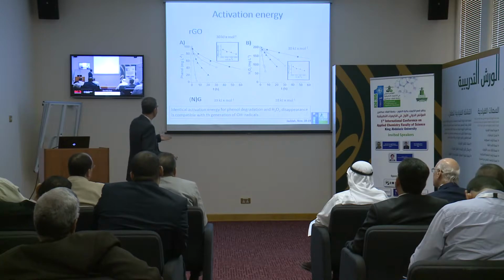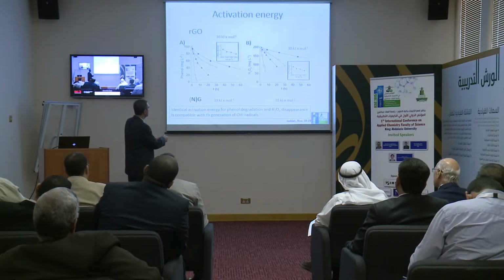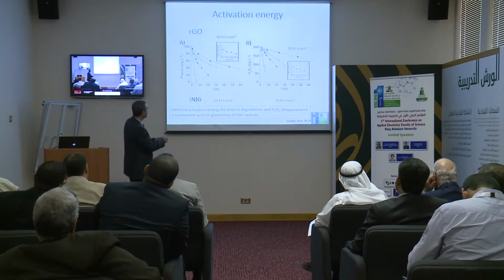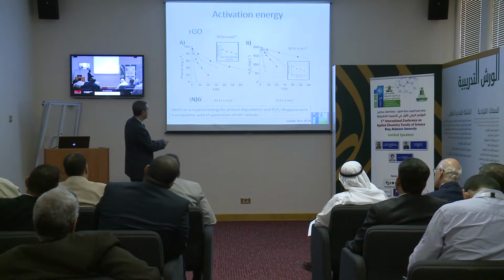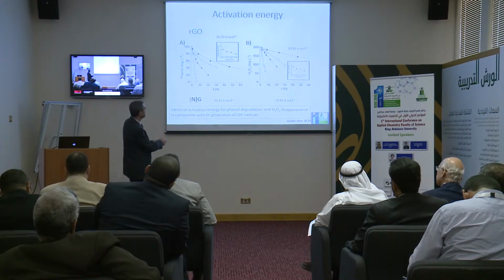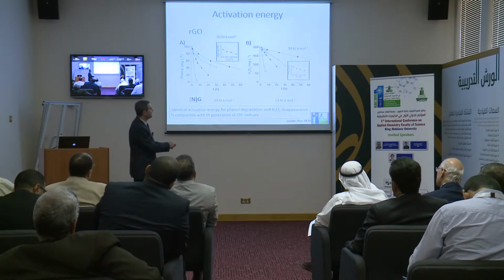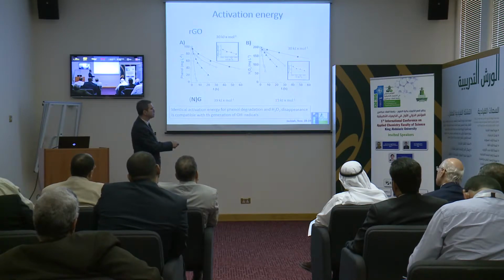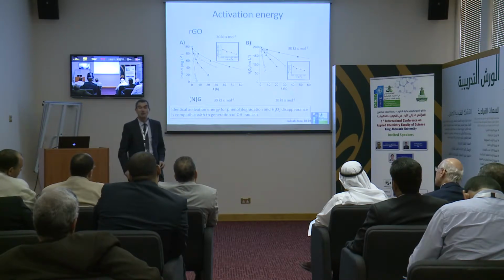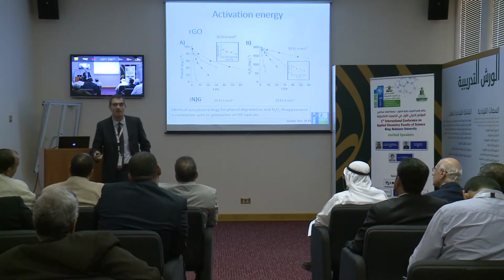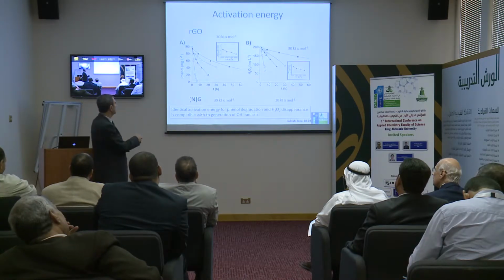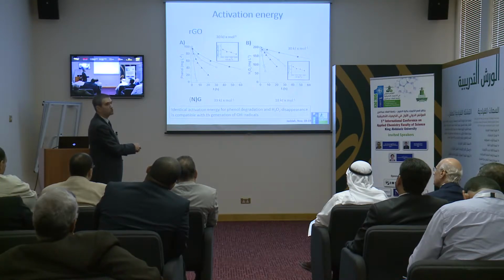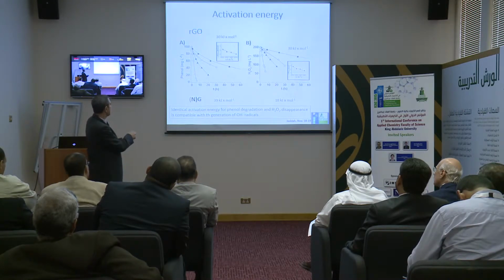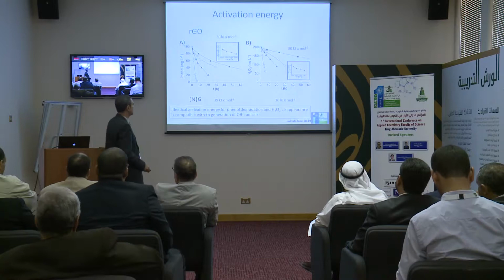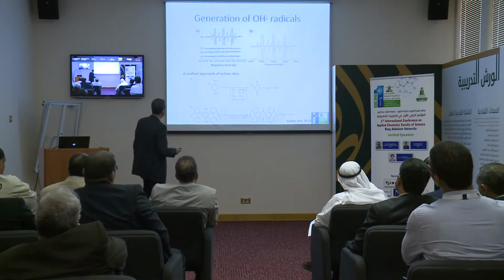However, we have other graphene, for instance, graphene doped with nitrogen, that is not very good. And here, for instance, the activation energy is much higher. But not only this, for hydrogen peroxide decomposition, the activation energy is lower. So this means that this graphene is very good for the decomposition of hydrogen peroxide, but without leading to the degradation of phenol. So it decomposes hydrogen peroxide very fast, but it does not degrade phenol, while this other graphene is very good for both things. So it's a hallmark of the Fenton chemistry.